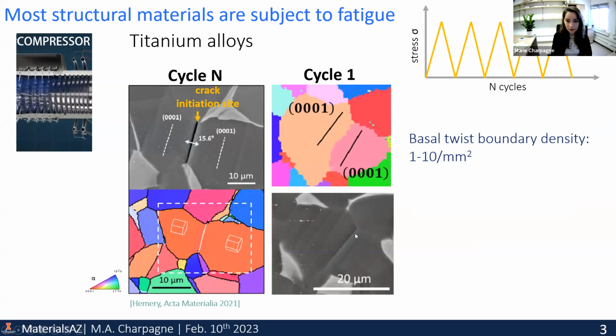And so early on, this hints towards the fact that we already have some signature of what's going to become a crack eventually when we add cycles. One bad news, though, is that the density of these twist boundaries is very, very low. We have just a handful per square millimeter of material.